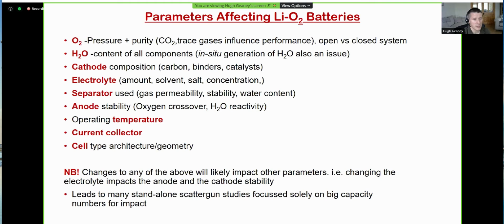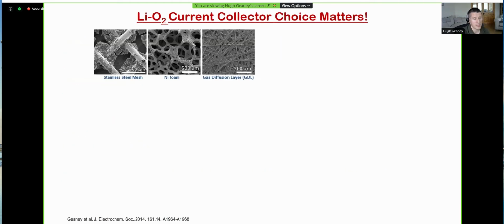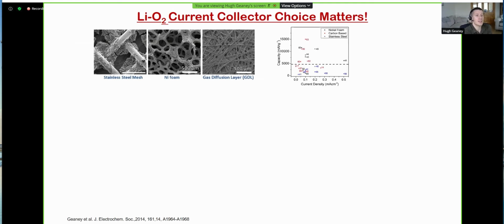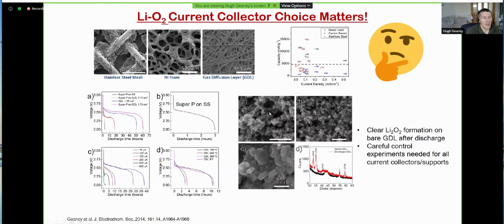Now, there has been lots of progress and lots of really nice understanding developed around the mechanistic side. The 2 very brief papers that I'll talk about were work that I had done in UCC. So in terms of the current collector choice, it really does matter. We have types that are used: a stainless steel mesh, nickel foam, or gas diffusion layer, which is a carbon-based electrode. So what I found when I was analysing the data on this, suspiciously, at least in my mind, was that the highest capacity numbers seemed to always be for carbon-based and nickel foam-based electrodes, whereas the stainless steel-based current collectors were usually much lower.